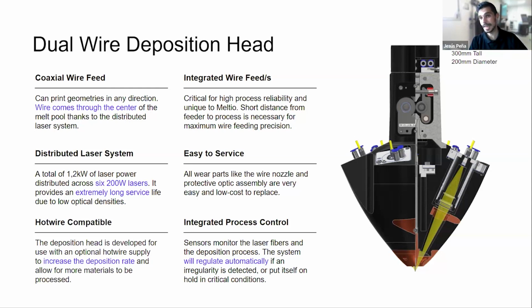So we have this current flowing in the head, and of course, we also have a control that is a pick-up coming from the backside of the head that is measuring the voltage that you have all the time in the melt pool. So as soon as you have any disconformity in the deposition, if there is any rise in the voltage of the melt pool, then you will have a correction directly done by the electronics that Meltio has.